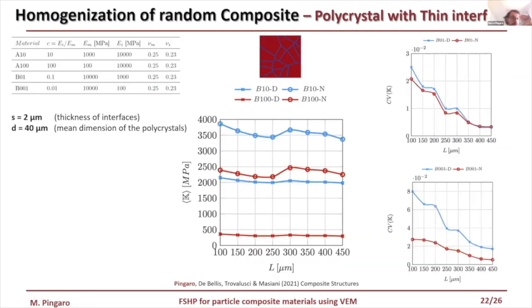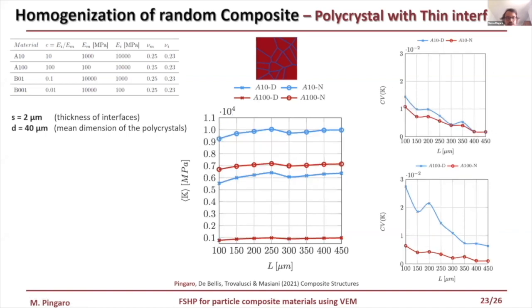After that, we started to study, we consider four constant contrast of material, 2 for stiff and 2 for soft grains, respectively. And in this slide is reported the bulk modulus at varying the window dimension for soft inclusions and the relative coefficient of variation. It's possible to obtain the same results for the stiff inclusion. More or less the trend is the same.